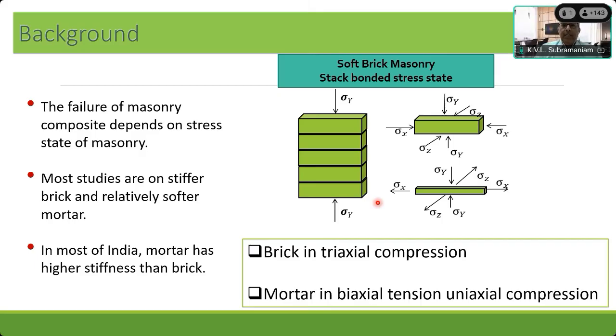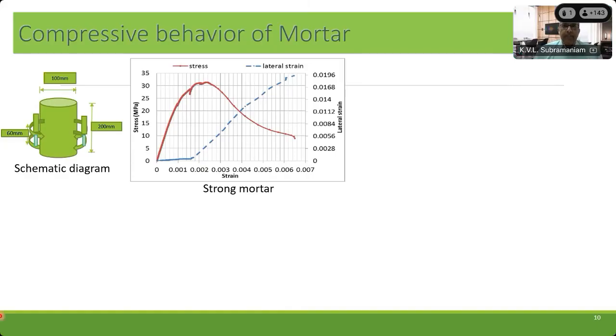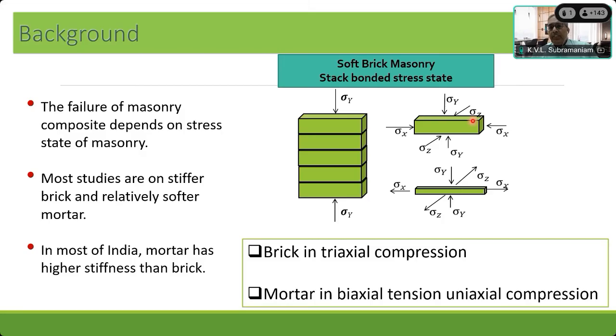Okay. Right. So now let me show you the compressive behavior of mortar. Remember what I said, going back here: we said both the brick and the mortar are classically quasi-brittle materials, which means both brick and mortar will have a compressive strength which is higher than the tensile strength. Both materials are weak in tension and strong in compression. And because the properties of these two materials are different, although I apply a uniaxial compressive stress on the masonry, I end up producing a triaxial state of stress in the masonry.